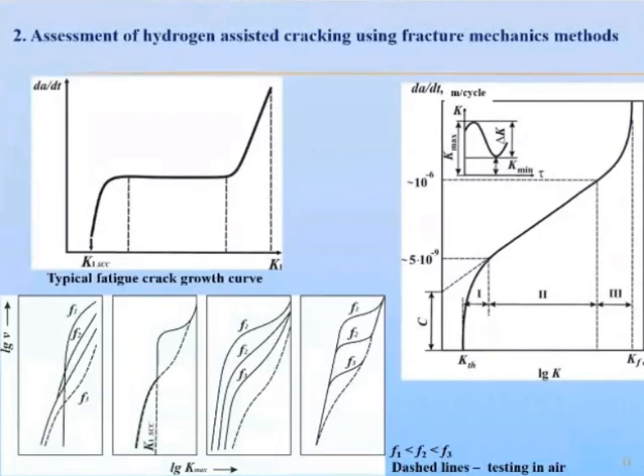Assessment of hydrogen-assisted cracking using fracture mechanics methods. Generally, two types of mechanical loading are used, static and cyclic. For the first one, the crack growth rate as a dependence on stress intensity factor and a threshold stress intensity factor characterize fracture resistance. And for the second one, a corresponding dependence of fatigue crack growth rate on delta K and fatigue threshold delta KTH. And there is a constant level of crack growth rate in a wide range of stress intensity factor range.